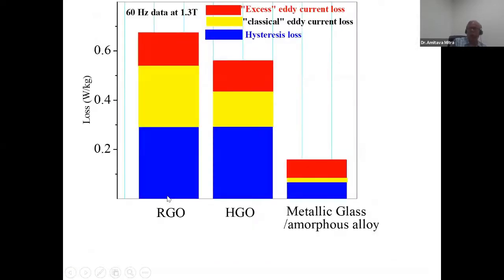If we plot now the same curve compared to the regular grain oriented or high grain oriented silicon steel as compared to the amorphous or metallic glasses, there is a drastic difference in the loss of energy, that is the area of the hysteresis loop - this is the hysteresis loss, this is what I call classical eddy current loss, and this is the excess eddy current loss. This loss is reduced because this amorphous alloy has high resistivity.